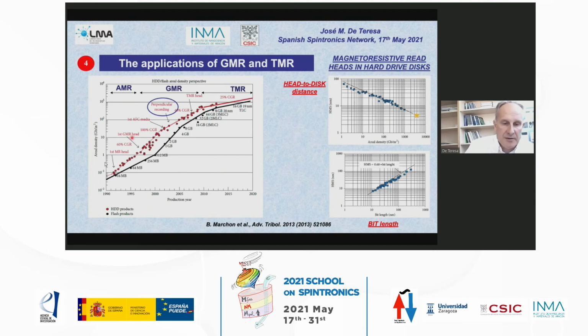The first GMR head was introduced in 1997, only 9 years after the basic discovery took place by the groups of Peter Grünberg and Albert Fert. And the advantage here was that the magnetoresistance effect was higher. Then there was another step in the technology in around 2003, in which the technology changed from bits with in-plane magnetization to bits with perpendicular magnetization. This is called perpendicular recording, and then the footprint of the bits could be smaller, and this was the reason to change from in-plane magnetization to out-of-plane magnetization.